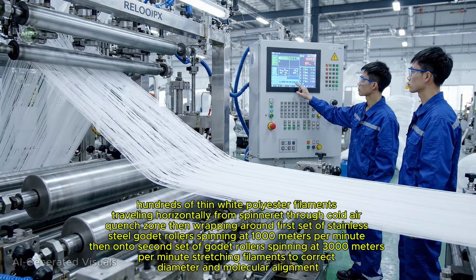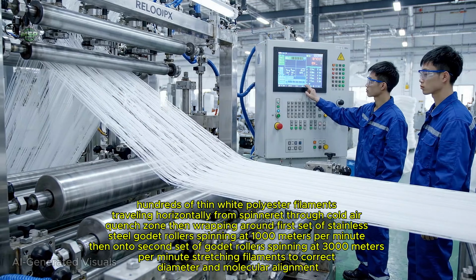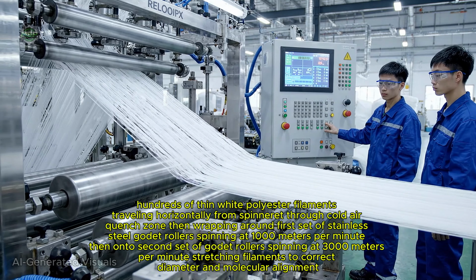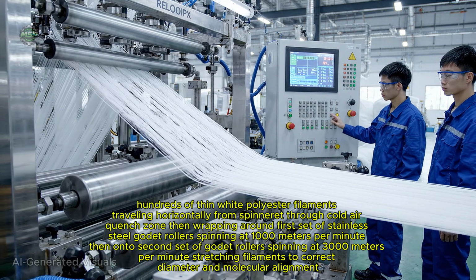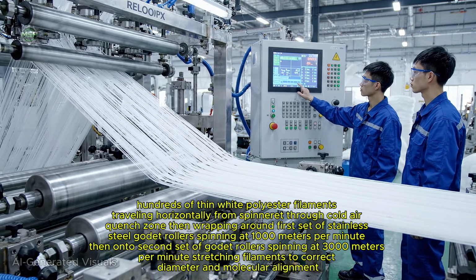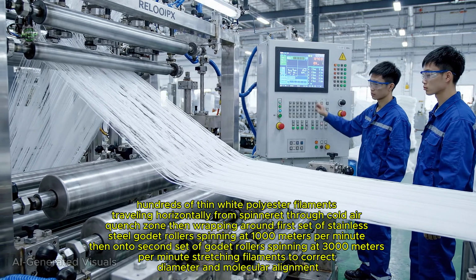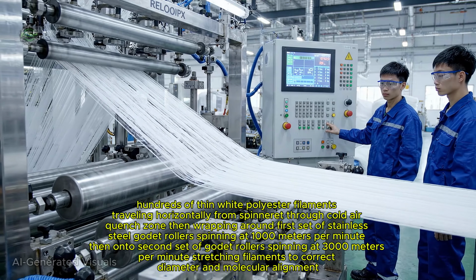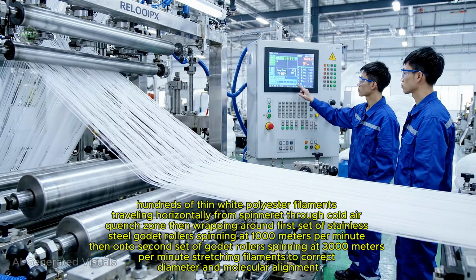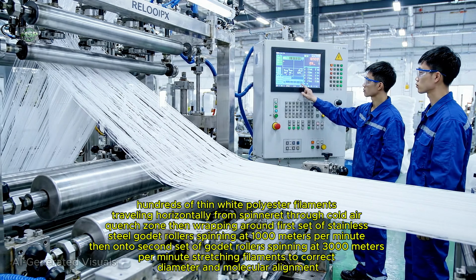Hundreds of thin white polyester filaments travel horizontally from the spinneret through a cold air quench zone, then wrap around the first set of stainless steel Godet rollers, spinning at 1,000 meters per minute, then onto a second set of Godet rollers, spinning at 3,000 meters per minute, stretching the filaments to the correct diameter and molecular alignment.